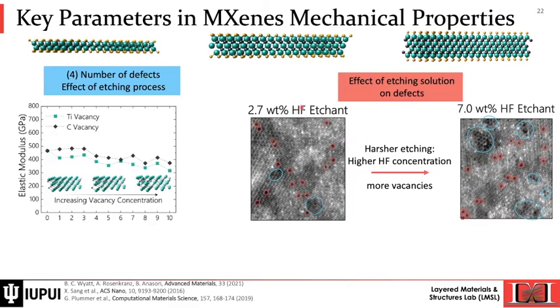Each of these, while we are removing the A group elements, we also create vacancies by removing some of the transition metals such as titanium or carbon from the structure. By introducing these defects in the structure just by using higher HF concentration or harsher etching conditions, it can be higher temperature, we can create more vacancies, and that can also change the elastic mechanical properties in general of the resulting MXene. This is shown by just increasing the number of vacancies in titanium or carbon atomic sites in Ti3C2.